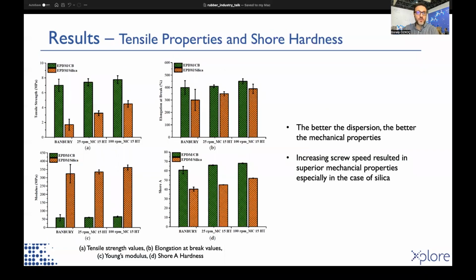Of course, the level of dispersion has an impact on the resulting mechanical properties of the vulcanized samples. The mechanical properties of EPDM compounds are represented in the figures in the slide. Tensile strength data revealed that the tensile strength obtained from the microcompounder was higher than that of Banbury. This was possibly due to the better dispersion of the fillers, both carbon black and silica. Increasing the RPM in the microcompounder from 25 to 100 resulted in improved tensile strength independent of filler type.